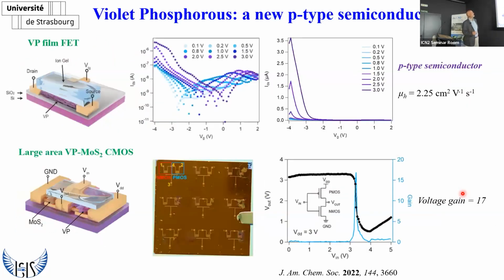Now, with these isolated flakes, we first of all fabricate a field effect transistor using the ionic gel, so to use the volumetric gating, and we detect the mobility. It was about 2, which is not too bad. And then by combining, we fabricate an inverter in which we use molybdenum disulfide as N-type, and the violet phosphorus as P-type. And this led us to a voltage gain in our device of about 17. That is among those that have been reported for state-of-the-art, or hafnium oxide, that is the reference type of devices for this kind of inverter.